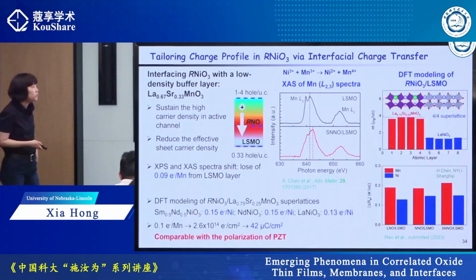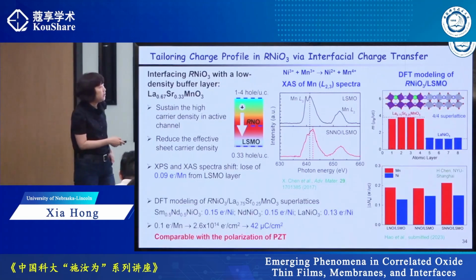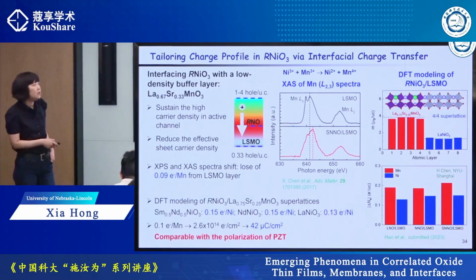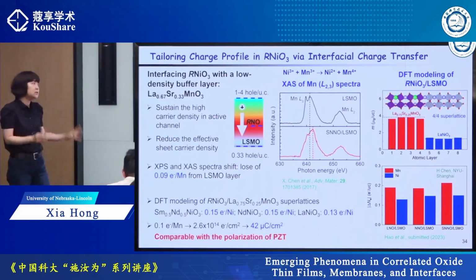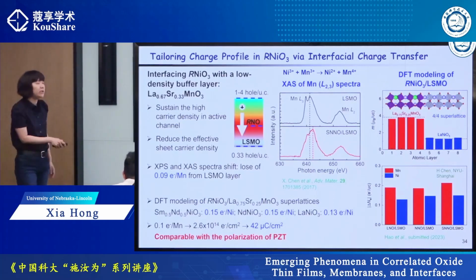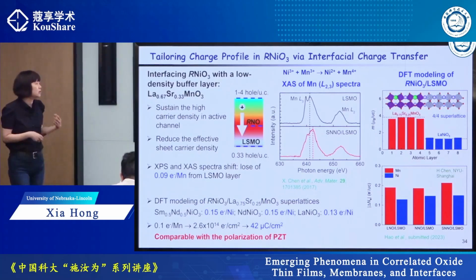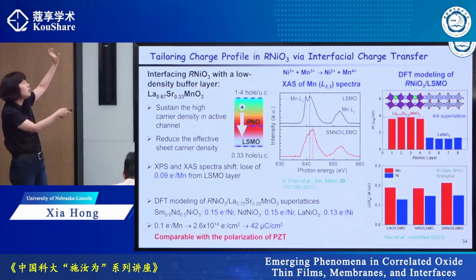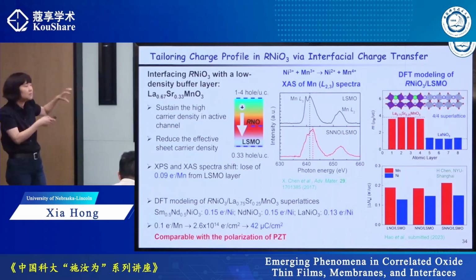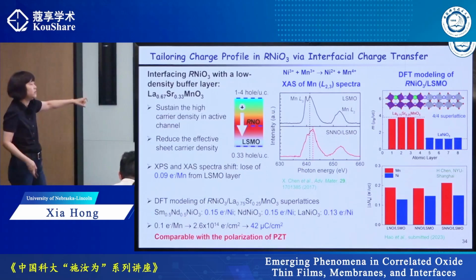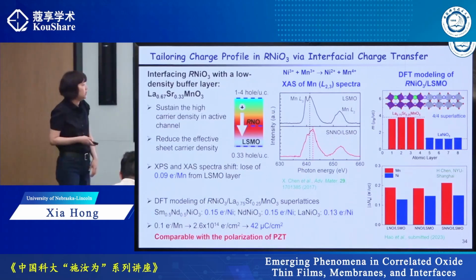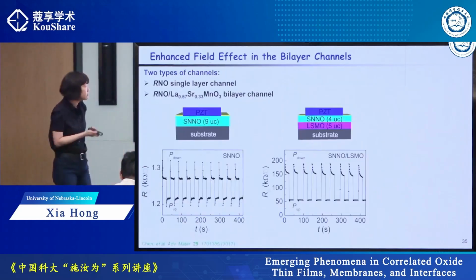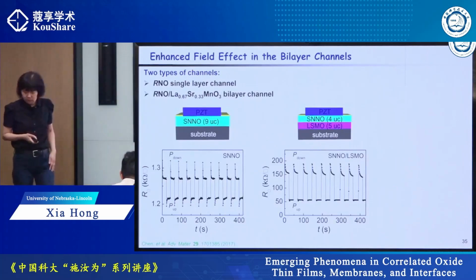And you can see that if you compare different combinations of nickelate with LSMO, it is more or less the same magnitude effect. This is huge, because if you calculate what the 2D density corresponds to, it's actually comparable with the polarization of PZT. So I have a top gate PZT and a bottom modulation comparable with that. So I doubled my modulation capacity. And let me just show the effect.